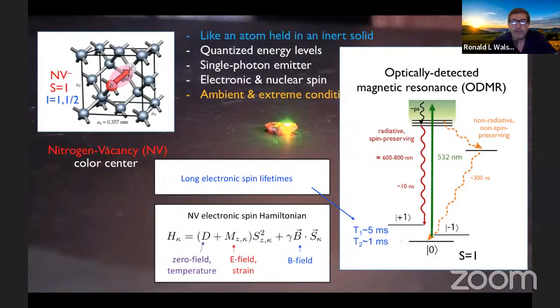Other key points. The electronic spin lifetimes of the NV, the spin lattice relaxation time, known as T1, and the spin coherence time, known as T2, are remarkably long, even at room temperature. It can be milliseconds long. Think about that. That's an electronic spin sitting inside of a room temperature solid with all the vibronic and phononic processes that are going on inside that room temperature solid. And still, the electronic spin is so isolated from the excitations inside the diamond because of the special nature of the NV, its small spin orbit interaction, and the fact that the NV energy level structure sits midway between the valence and conduction bands, that you can have remarkably long coherence times.